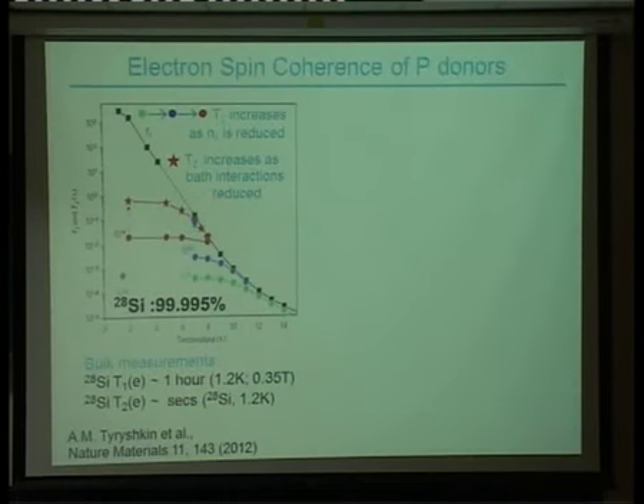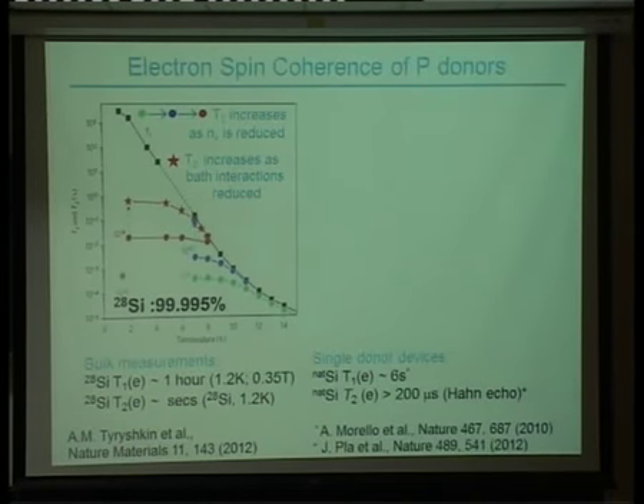This is using the electron spin. Very recently in the Australian group, using the ion implant route, they've been able to measure a T1 time of 6 seconds and a T2 time of 200 microseconds after the Hahn echo sequence. All of these are really promising reasons why silicon is a good system to look at.